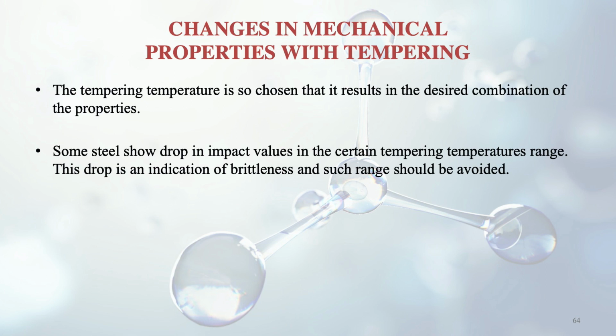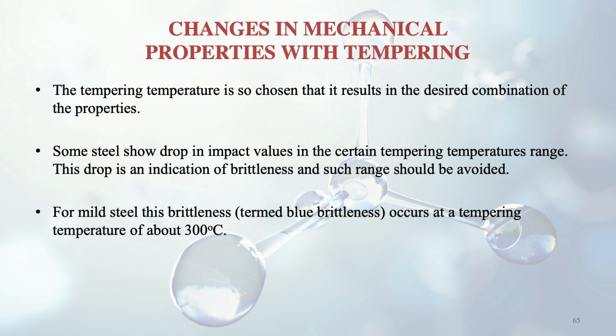Some steels show a drop in impact values in a certain tempering temperature range also. So this drop is an indication of what? Brittleness, because toughness will decrease and brittleness will come in, and this range should be avoided. For mild steel, this brittleness, which is also known as blue brittleness, occurs at a tempering temperature of about 300 degrees centigrade. So for mild steel we will have to avoid this temperature of 300 degrees centigrade.